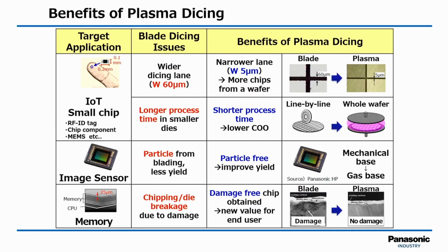So if we look at the benefits of plasma dicing lined up against blade dicing, for small chips, we can see with the blade dicing a dicing street width of 60 micrometers, we can go down to even 5 micrometers with plasma dicing, increasing yield. Process time can be much shorter because, as I said, the dicing is performed on the whole wafer at once. So instead of it being based on line-by-line time, it's more based on the thickness and the composition of the wafer.